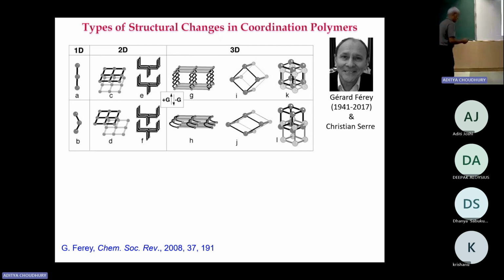And he classified the types of structural changes, okay, how they can happen. In the case of 1D, it can bend. By bending, the structural change can occur. Not in terms of single crystal, but in the structure. If you take a look at the X-ray data before and after bending, there'll be a change. If it's a 2D, it breathes out, and the distance increases and decreases, or it can slide also because of this. Okay, it can slide, or it can increase straight away. Or when you have a 3D, when you have a spring-like thing, it can compress, or it can go in different ways. So things are happening. We can see it in a mechanical way, but this is really happening in the molecular structure, especially in MOF structures, when you determine the structures using single crystal X-ray crystallography.